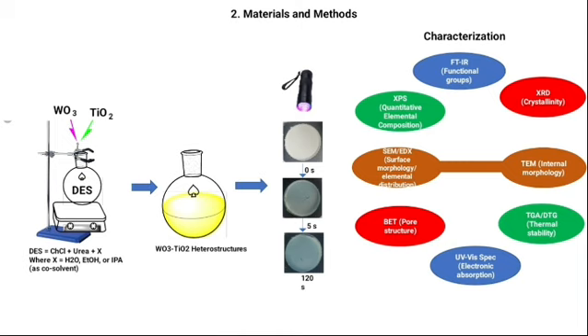In the preparation, the eutectic templates containing 3.4 gram of choline chloride and 1.5 gram of urea were prepared using different co-solvents, which include water, ethanol, and isopropyl alcohol, which were made in separate flasks, and these mixtures were heated in thermostated oil baths at 80 degrees for 30 minutes to first obtain a clear solution.